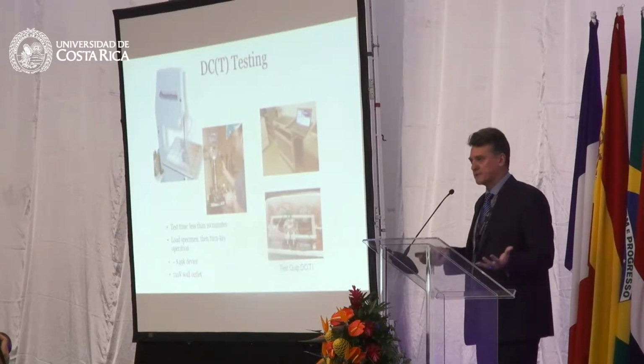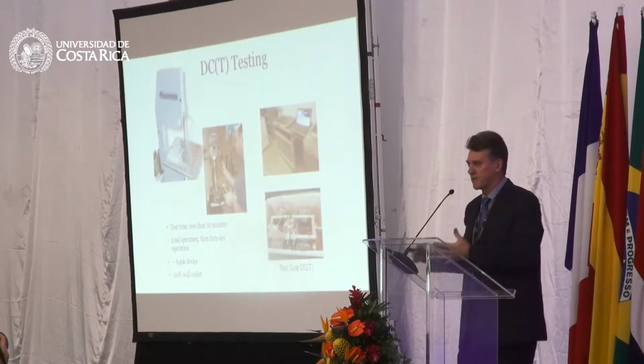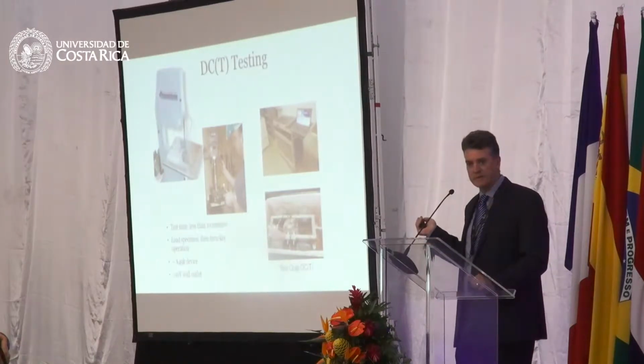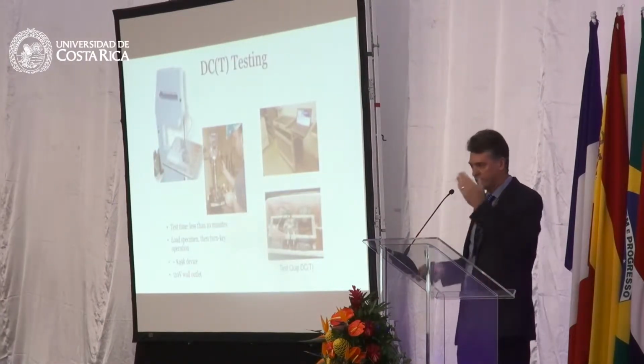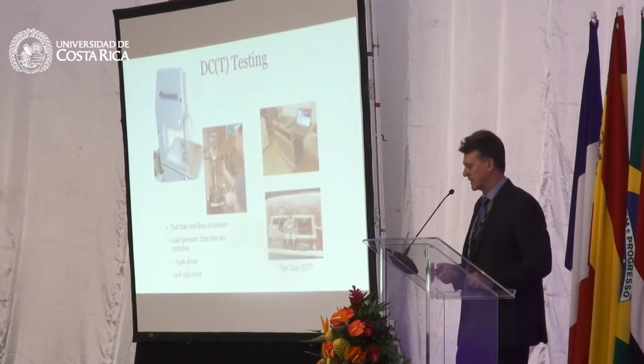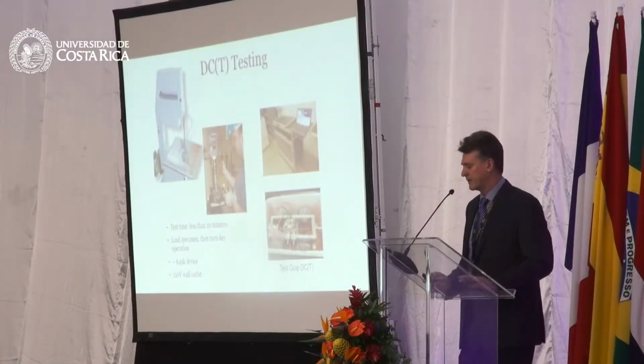If you make specimens in batch, maybe 8 or 10 at a time, it takes about 10 minutes on average to do the cuts you need and the drilling of the holes. So it's not terribly cumbersome.